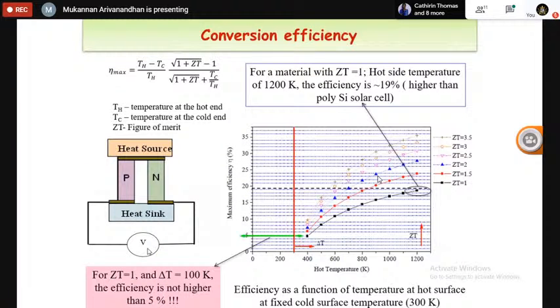But what is the current scenario of this thermoelectric technology? You can see the thermoelectric efficiency is not up to the level. It is not up to the range of silicon-based photovoltaics, because the silicon-based photovoltaic is a well-matured technology, where you can have a conversion efficiency in the range of 15 to 20%, based on the kind of silicon wafer used for the solar cell. And also you can have a lifetime of about 15 to 20 years. But the commercialization as well as the performance of thermoelectric technology is not up to the level.